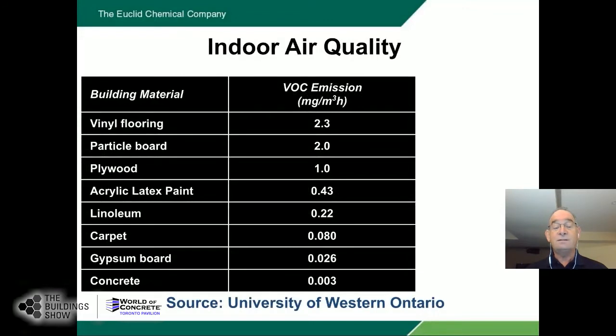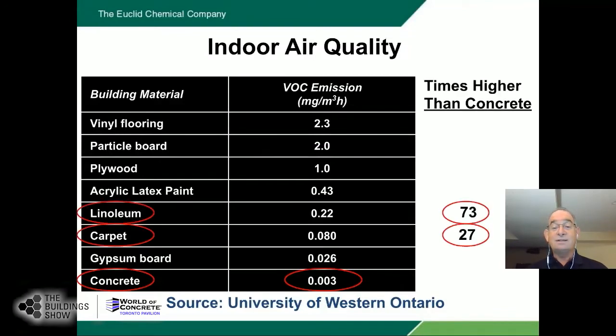A survey or a test program was done at Western University a few years ago just to compare different floor methods. And this all came about because of LEED situations where they're considering removing tile or wood laminate, that sort of thing, and just have exposed concrete floors. When you're dealing with concrete, the VOC emissions in milligrams per cubic meter per hour is 0.003 for concrete. For carpet, it's 0.08, 27 times higher than concrete. For linoleum, it's 0.22, or 73 times as high as concrete. And when we get to vinyl flooring, it's 2.3 milligrams per cubic meter per hour, 767 times that of concrete. So you can see why a lot of these projects tend to go with low VOC materials if possible. And by using concrete, you can't get any lower than that as far as a finished floor material.